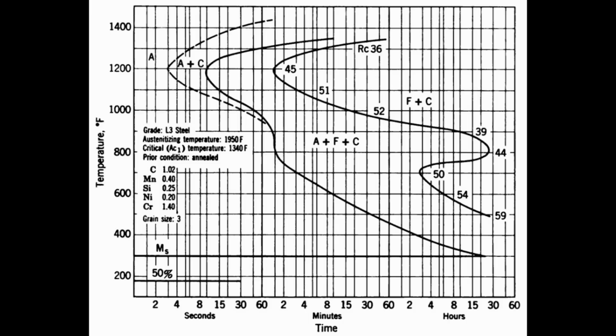However, the austempering time has also increased. So the kinetics of the transformation, how long it takes for the transformation to occur, is now longer because of that extra carbon and alloy. That makes the bainite take longer to transform. So now, when holding at 500 degrees Fahrenheit, instead of 2,000 seconds to fully transform, around 30 minutes, it's taking over 15 hours to transform.